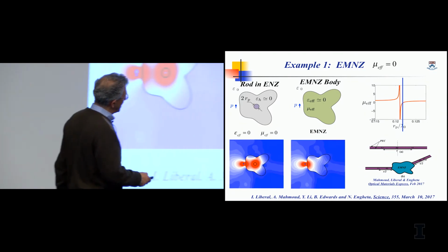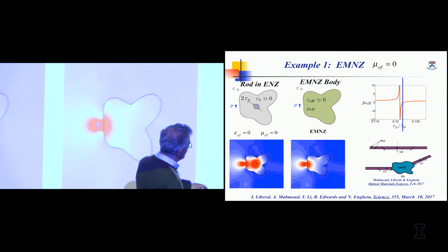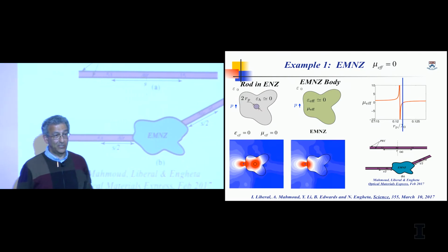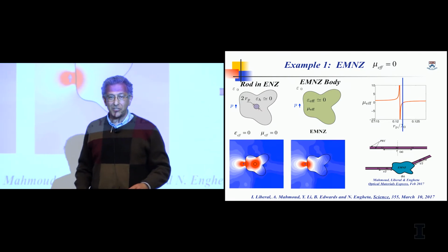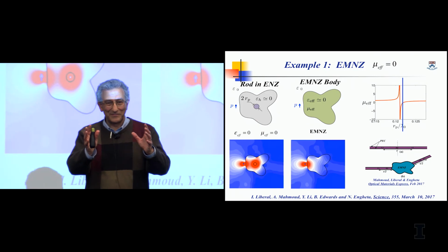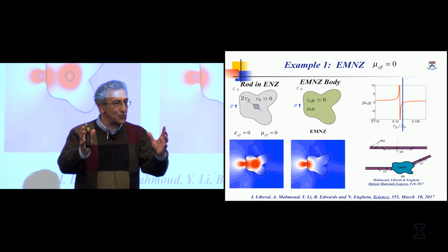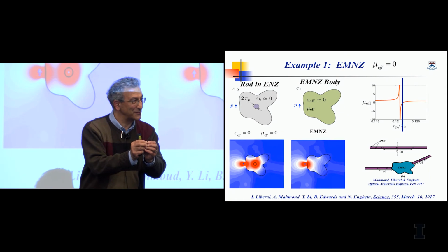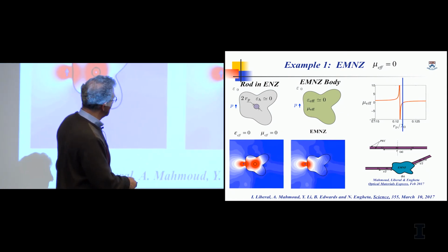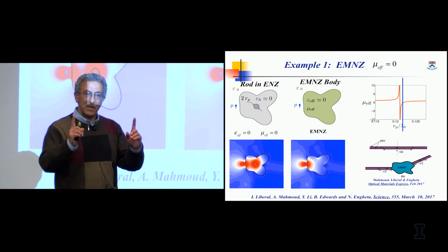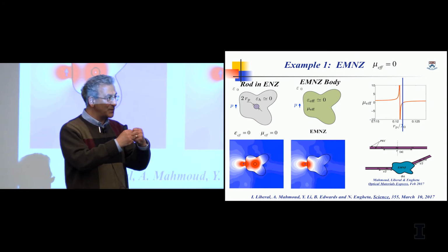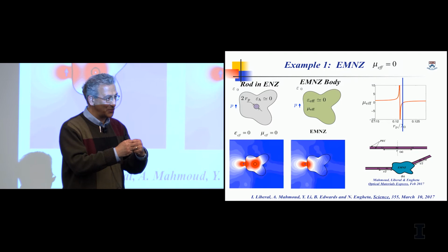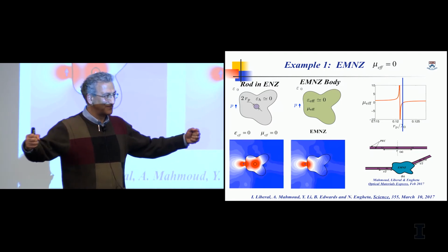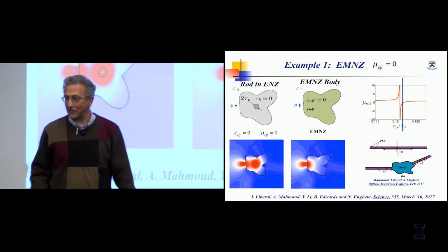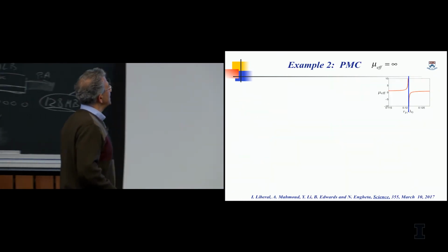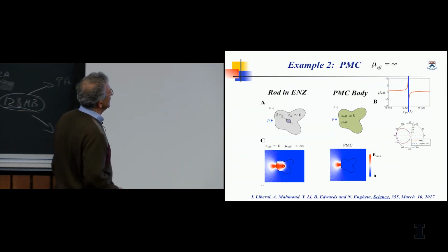So as a result, you can think about this blob of structure whose epsilon and mu are near zero. That means the wavelength becomes infinitely large. That means even though you have a structure that is physically any size you want, electromagnetically it is one point. Which means if you put two quantum emitters here and there, the quantum emitters interact and entangle with each other just like they're in the near field of each other, even though they're far apart, because that region actually behaves as a point. And you can actually have a magnetic mirror as well to do that.